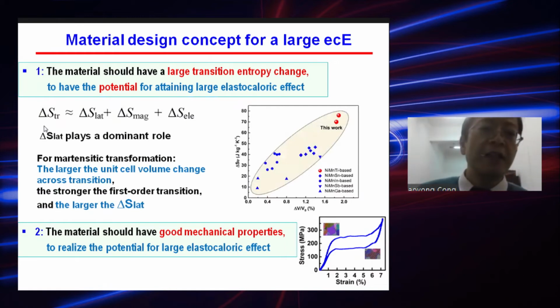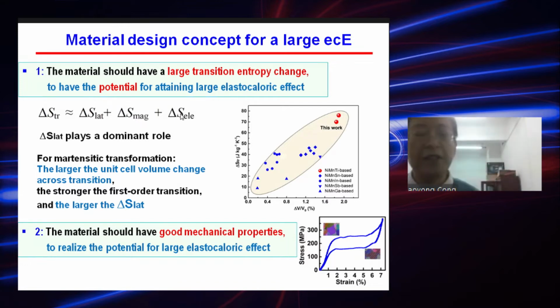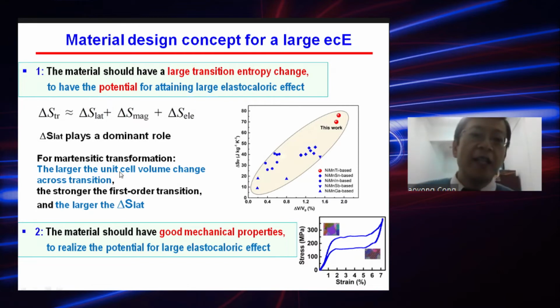Note that for shape memory alloys, transformation entropy change mainly consists of 3 parts: lattice entropy change, magnetic entropy change, and electronic entropy change. Among these, the lattice entropy change plays a dominant role. Especially for martensitic transformation, the larger the unit cell volume change across the phase transition, the stronger the first-order transition.